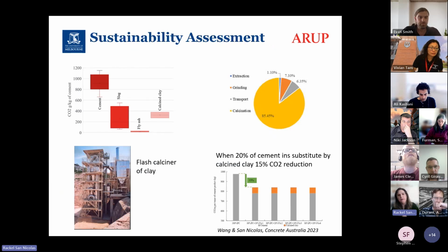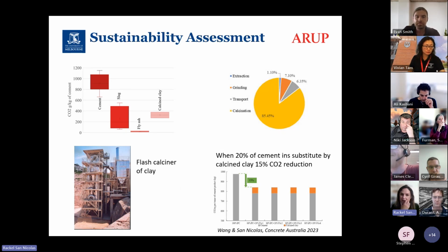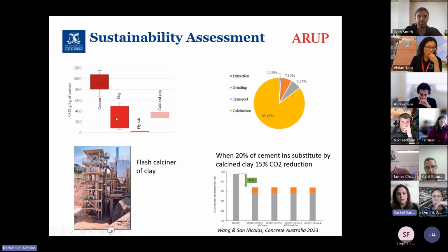So, the sustainability assessment of calcined clay. According to the data that we have, here is the region of cement slag, which can be from low to high depending on where you get it from, especially because if it's locally sourced and it's from our steel industry, it's fine. But when you have to import it, it's going to come from much further. Fly ash, as I said, has a low embodied carbon per ton, and calcined clay is about in this region, so it's in between both somehow.